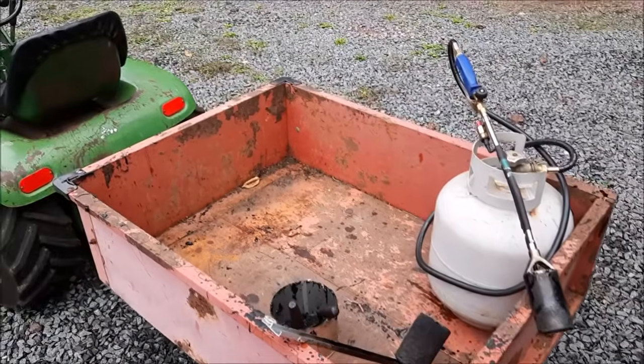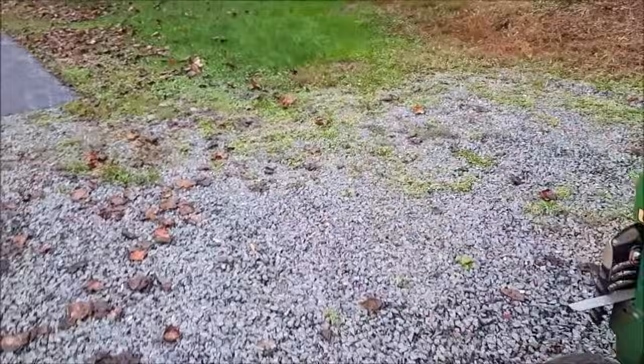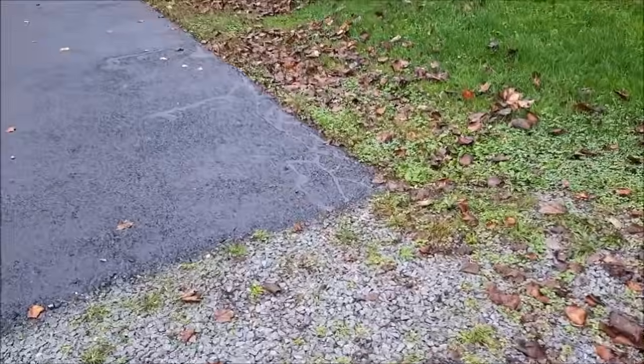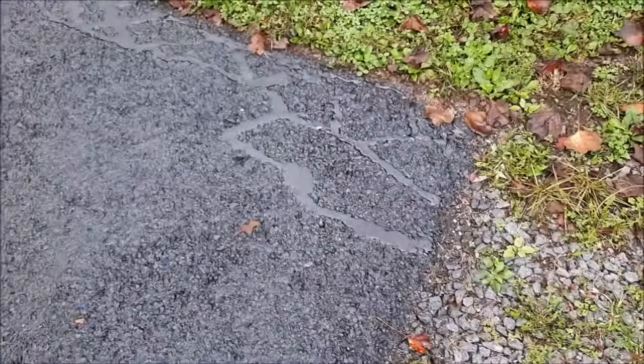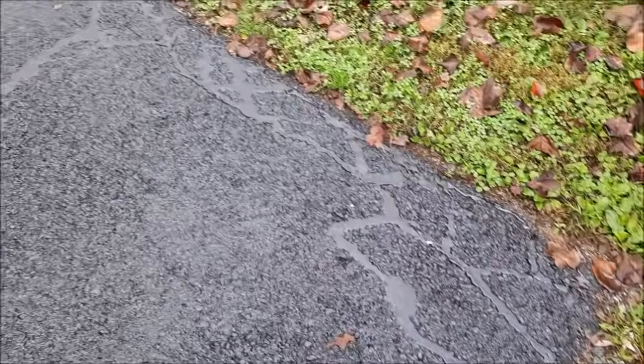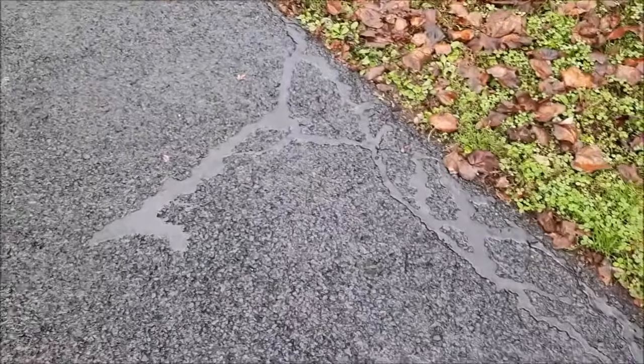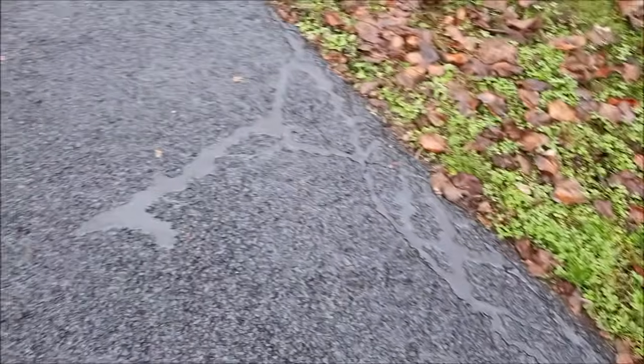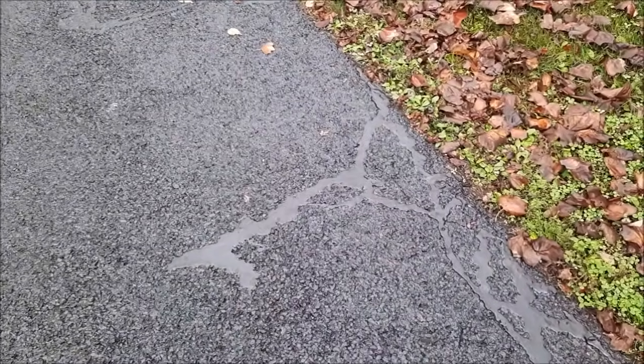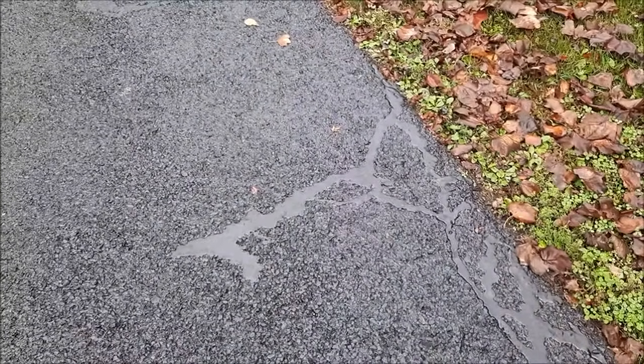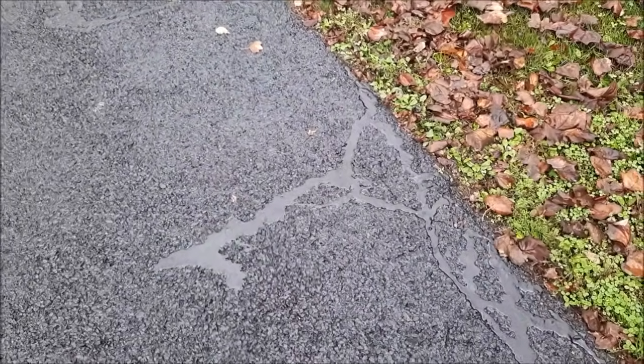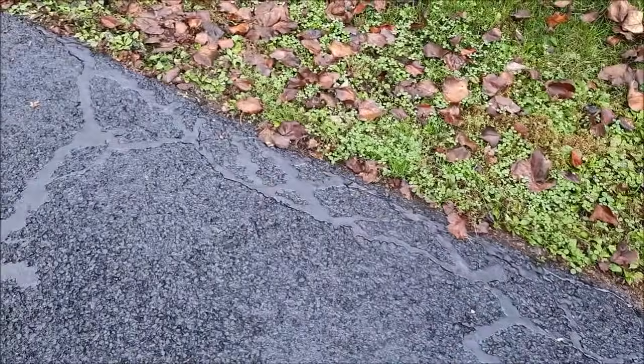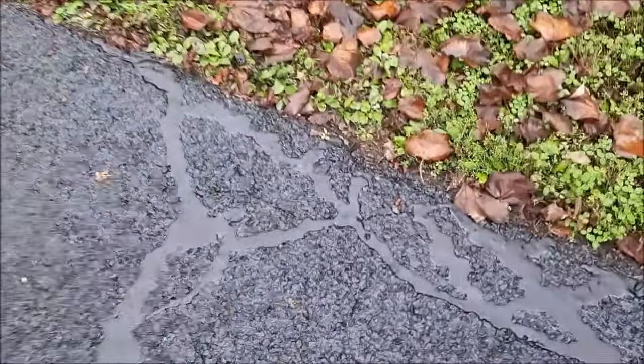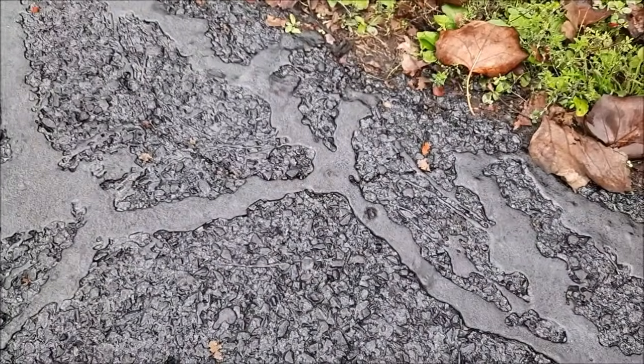And what I typically do is I'll walk the driveway, and you can see some of the spots here where I had sealed before they put the asphalt sealer down. He was really impressed that a homeowner, I think he said I was the only homeowner who had ever done this, that I went and sealed the cracks first, because in asphalt driveways, cracks are the killer. Cracks are the killer. So if you can seal them and keep your cracks sealed, it keeps the freeze-thaw cycle from opening up.